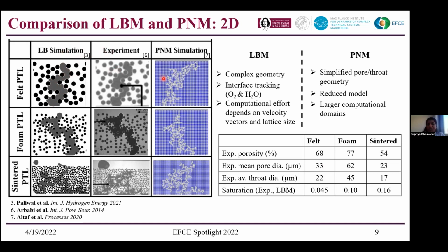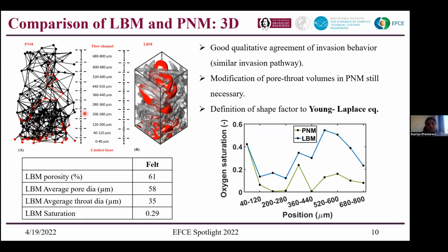Whereas in PNM, it was more of an idealized network where we simplified the experimental structure to a network of pores and throats. And then the reduced model based on the liquid pressures was applied. Whereas in LBM, you can also see that we could track how the oxygen moves and differentiate between the water and the oxygen. So this makes it computationally more effortful than what we see in the pore network model. So this is how we do it in 2D. And then in 3D, we use the irregular network of PNM, and we have our LBM simulation for the same commercially available felt.